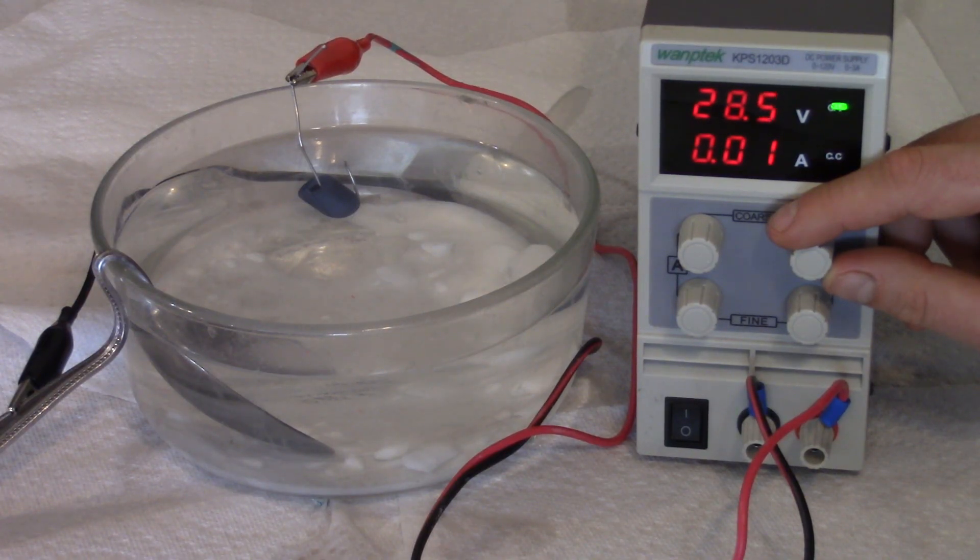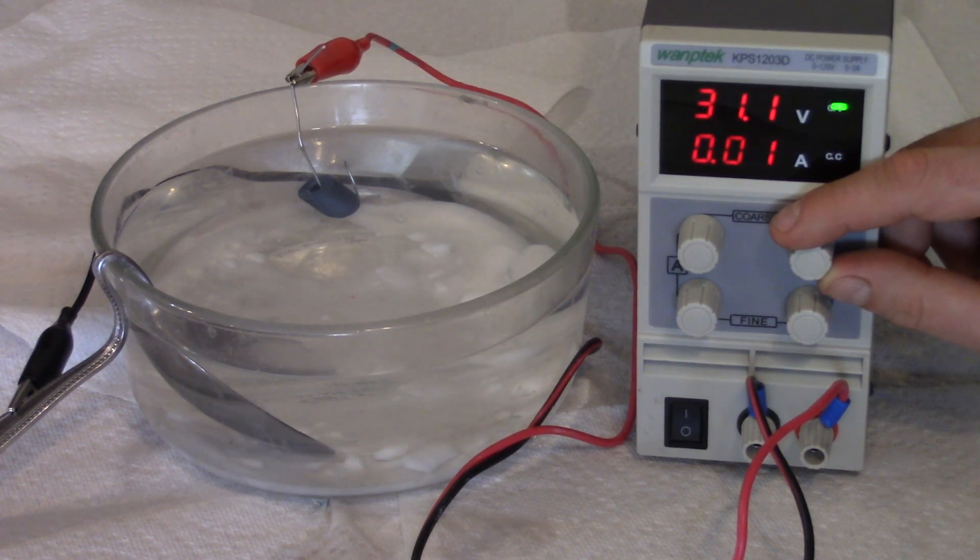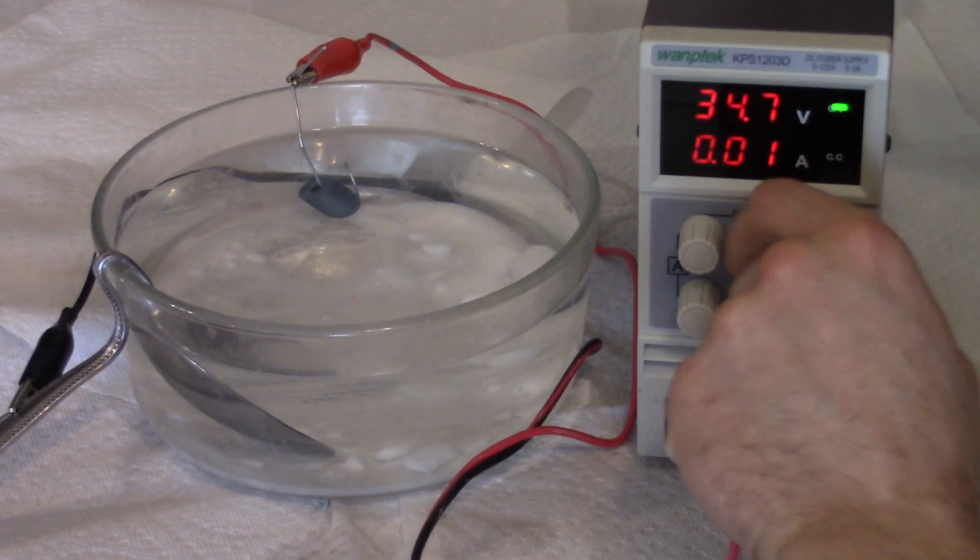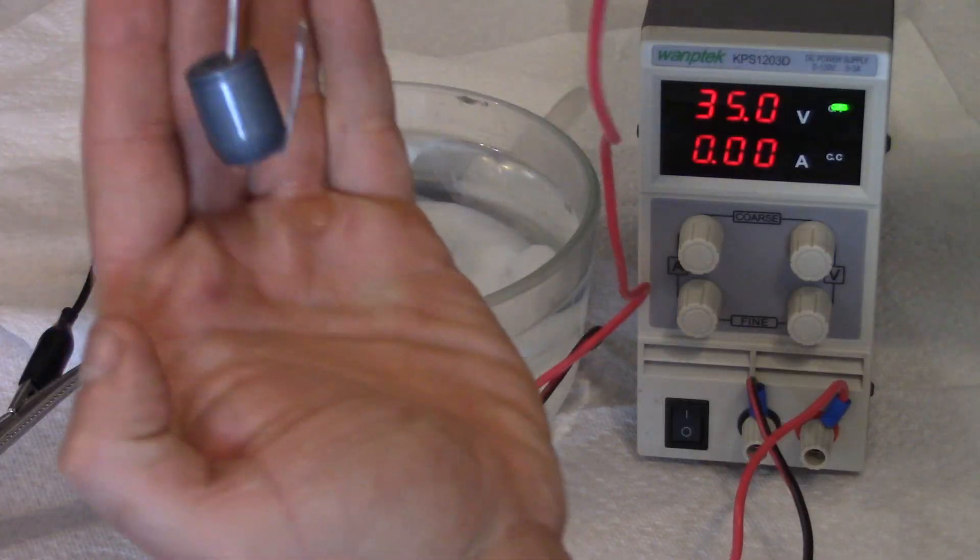See, as we slowly go up the blues start to get lighter and lighter and lighter. So if you want a dark blue you'd go for like 23 to 25. Pretty much 25 to 35 I know is all different shades of blue. So as you get around 35 it'll start to get like a silvery, like a stone really, or like old worn jeans look. See, as you can notice it's starting to get lighter and lighter blue. That's kind of a neat color right there.